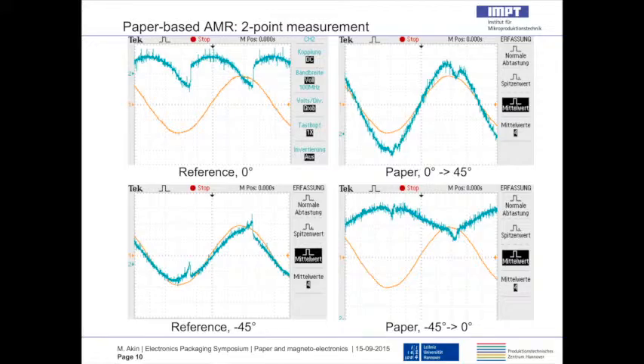Now, looking at the response of the paper-based system at the same angle between electric current and magnetic force, which is minus 45 degrees, well, the electric current, we would think, might happen along the magnetic stripe, but we obtain a response where the electrical resistance, the blue curve, and you see the second tip, that's very clear there, is increasing. So that's the 0-degree response you might basically obtain. So with the second experiment, we confirmed that the 45-degree shift is happening. And this is not dependent on the material. It seems like it's depending on the surface texture, and the same experimental result has been obtained whether using a 4-point contact measurement or a 2-point electrical resistance measurement.